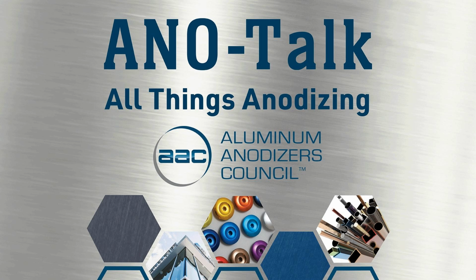That is the reason why, when you do pulse anodizing, it's even more important that you know your surface area. The whole idea of pulse anodizing is to have a higher average current density than the one you normally use. Because with a higher average current density, you will be able to decrease your process time and in that way increase your productivity.